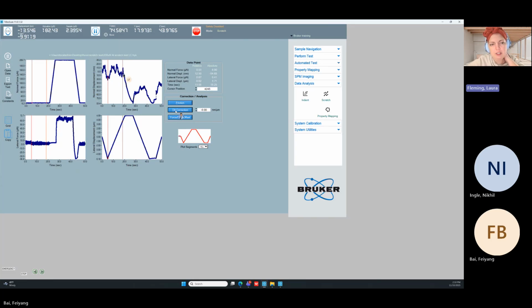So it's flattened this out. Now there is some bumps here. Aluminum is a weird sticky sample, so we're probably getting a little buildup. But you can see that that's what we've done here. And now we can be much more confident in our sample forces. So like here is where we loaded. And then as we started to scratch here, right, this is our scratch segment. It looks like we pop back up. So we probably loaded, and then as it scratched, it popped out of where the peak displacement was and slid, and then it probably dug itself in a little bit. So the aluminum's a little bit of a weird sample to be doing this on. Usually it's a little bit clearer, but hopefully that gives you an idea of what we're looking at.